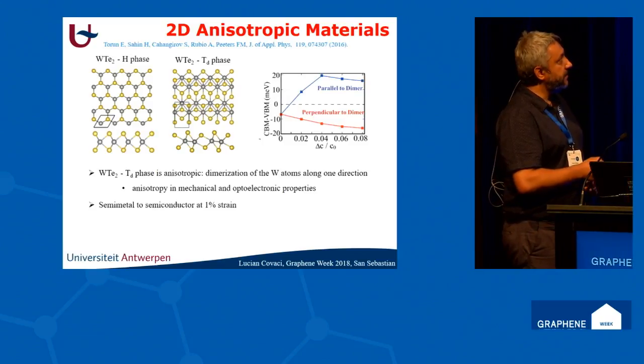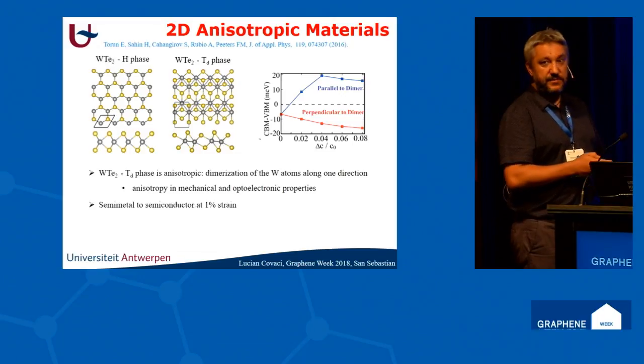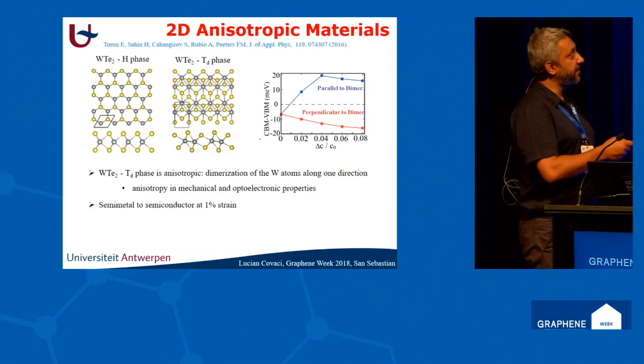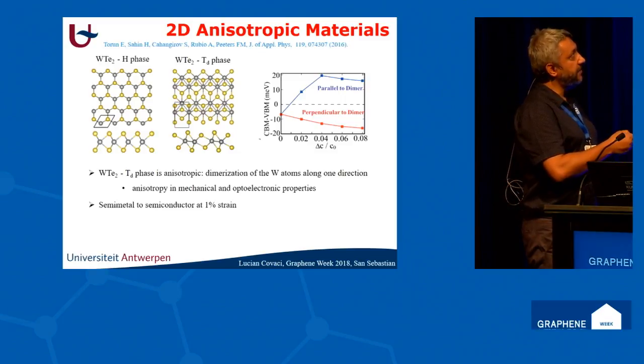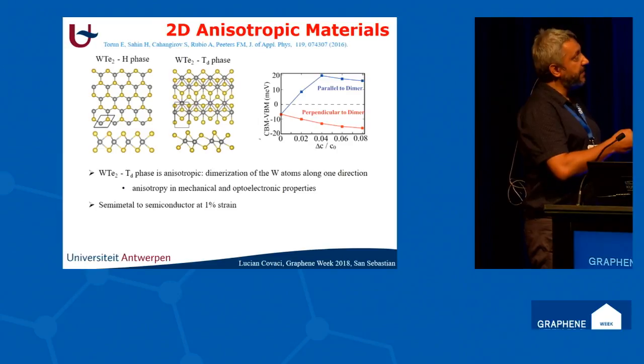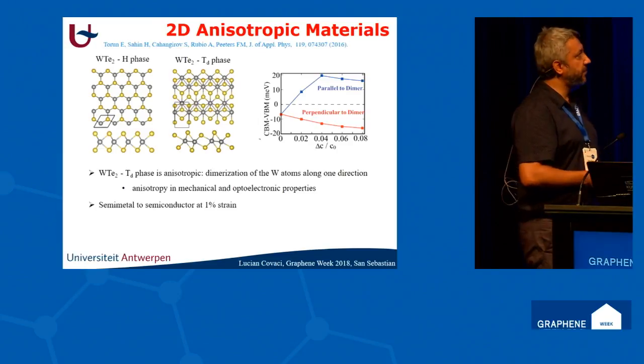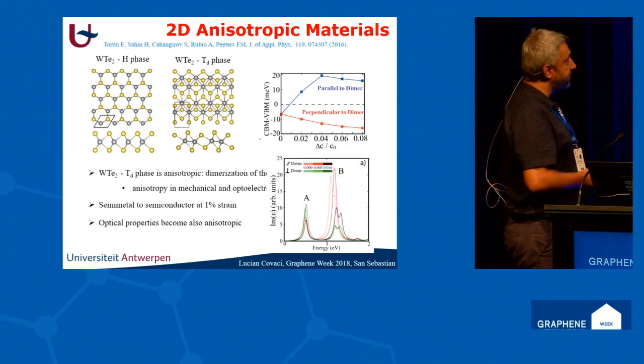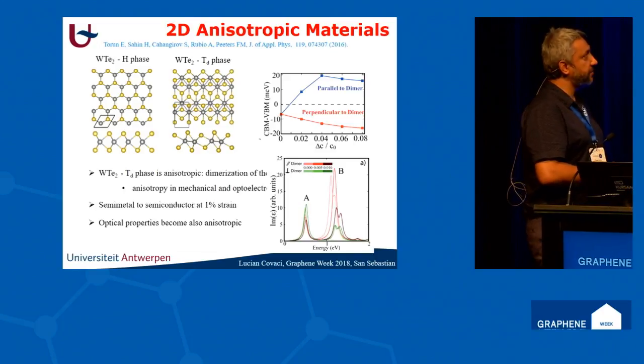And interestingly, because of the anisotropy, if you apply strain in different directions, like parallel and perpendicular to the tungsten dimer, you have either the appearance of a gap or a shift of the two bands. And optical properties also are anisotropic.